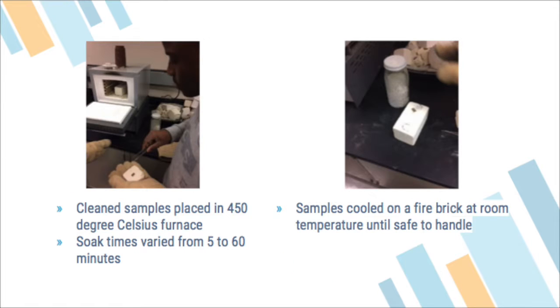The sample pieces were washed to remove the coolant. They were then placed in a furnace at 450 degrees Celsius for times of 5, 10, 20, 30, 40, and 60 minutes. Varying the times in the furnace would allow us to investigate how hardness and average grain size varies with the amount of time in the furnace under annealing conditions.